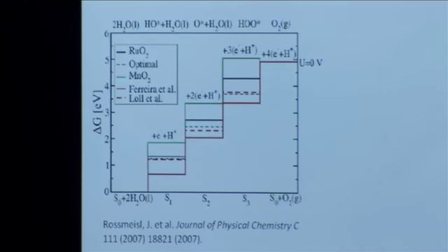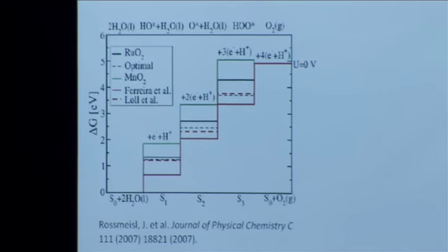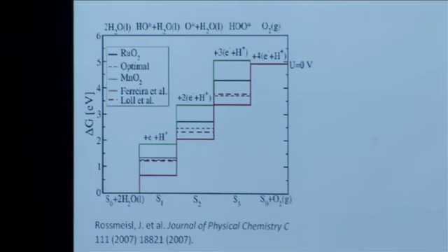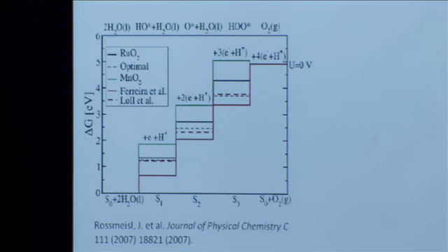In other words, these are the electrons and protons that you're pulling from water to make O2. And the point that I'd like to get across is if your electrode is sitting at 0 volts, that means you're 1.23 volts away from the equilibrium potential. That means that for you to go from this point to this point, you have to climb 4.92 electron volts in energy to get this reaction to go, just by thermodynamics. Okay, that's the absolute minimum.